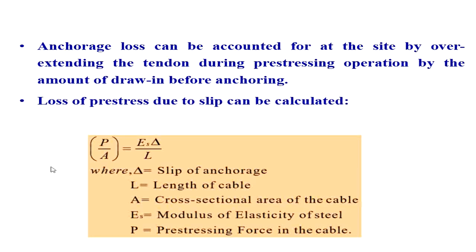Anchorage loss can be accounted for at the site by overextending the tendon during the pre-stressing operation by the amount of draw-in before anchoring.